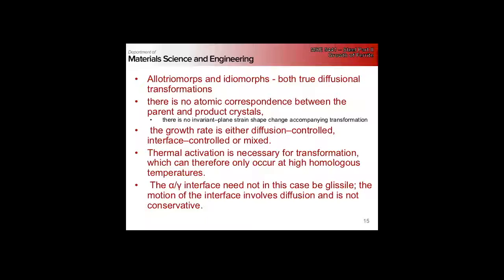Okay, so both of these occur by true diffusional mechanisms. We don't have any shear, we don't have an invariant plane strain shape change like we will with the Widmanstatten structures. The growth rate is either diffusion controlled or interface controlled.